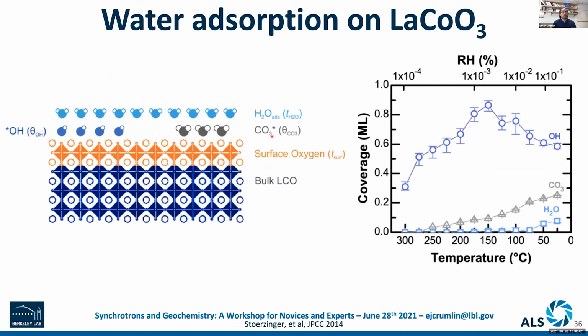And so if we bring all of this picture together, what's happening on the surface, we can start to make a really clear picture of how the surface of this lanthanum cobaltite is changing when you expose it to water, and understand the relationship with temperature, or convert it to a relative humidity, to when you're getting the maximizations of certain species and when they're converting and changing.